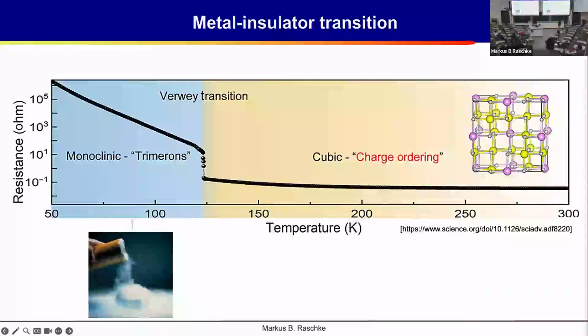And then there is a continuous increase again as you keep cooling, where the resistance increases. So this was discovered in 1940, and there was really no good explanation for this. This was the first quantum phase transition in a material discovered. It was that late. The experiment could have been done decades earlier. And it set off the field of quantum condensed matter physics, where it was recognized that compared to all these simple previous phases of liquid and solid and gas, now apparently we can switch a material from a metal to an insulator and back. And this mechanism is actually more complex than this magnetic behavior.